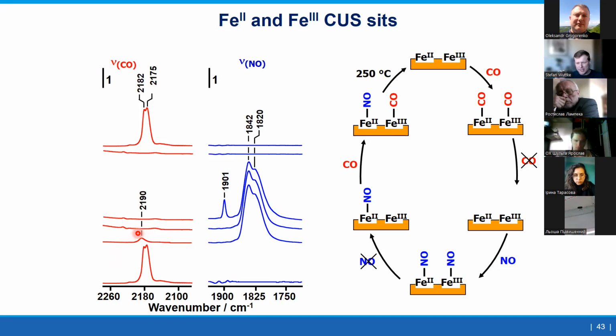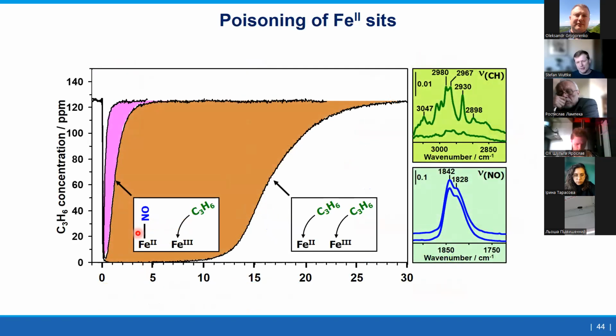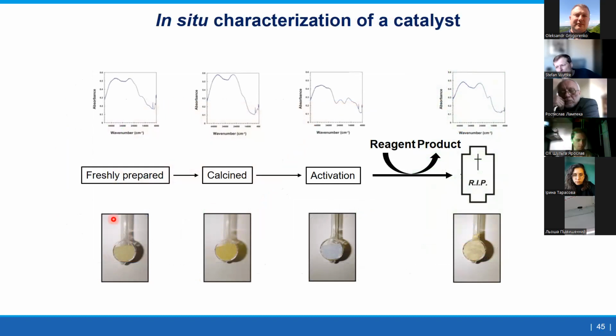And what we have here is that we can specifically poison iron 2+ with a species. And what we did then is the same separation when we had iron 2+ and iron 3+, and now poisoning iron 2+, and then we do the separation, and we can say, oh, iron 2+ is the main species for this separation. And if we know this, then we say, oh guys, we need a material with more iron 2+, because then the separation efficiency will increase. So you understand, and then you can advise the material chemist. So this is just an example of how you can really understand the sample easily and then improve something for separation. But going back now to the catalyst, here's a very important slide.